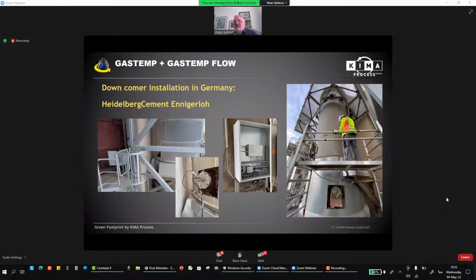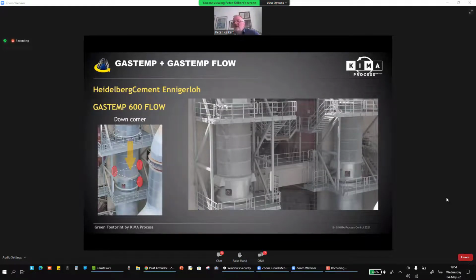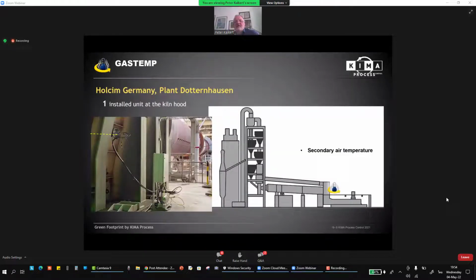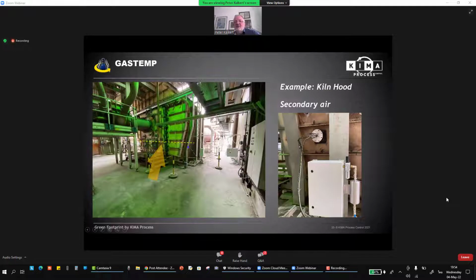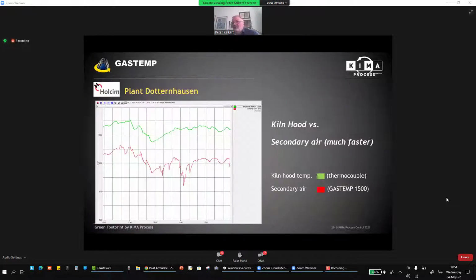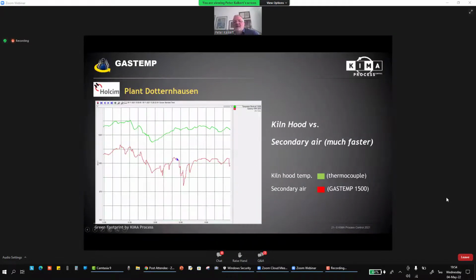Here we have, once again, another downcomer at a Heidelberg cement plant. What you see here is an installation at the kiln hood. In this case, we have measured the secondary air. This is a plant in Dotternhausen in Germany. Here you see the secondary air temperature as compared to a thermocouple. You see a soot blower was shooting, and our system could see this, while you would have completely missed this with the thermocouple.